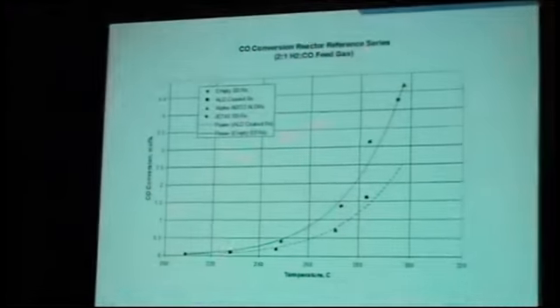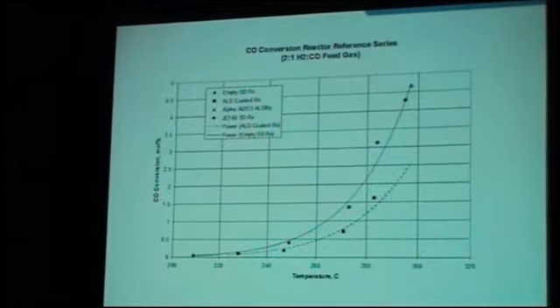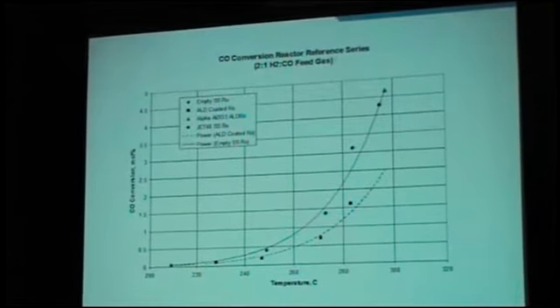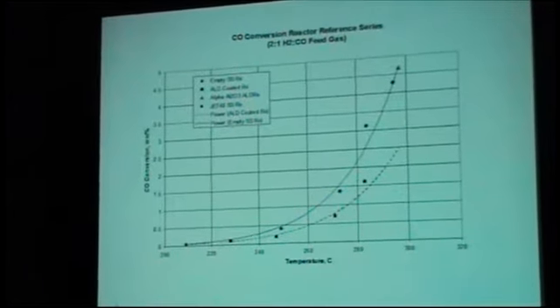You start out at low conversion levels, and you have an iron reactor, stainless steel reactor. If you have the stainless steel reactor itself, you get a degree of conversion over the temperature range, either with an alpha alumina catalyst or an empty reactor. We coated that stainless steel reactor with a little bit of alumina by ALD. You'll notice that it knocks down the amount of conversion so that we have a low level of background during the run.